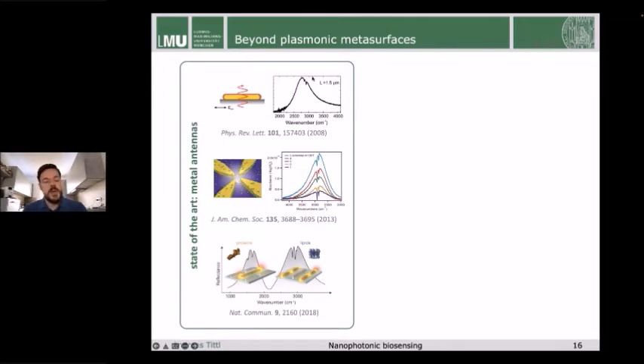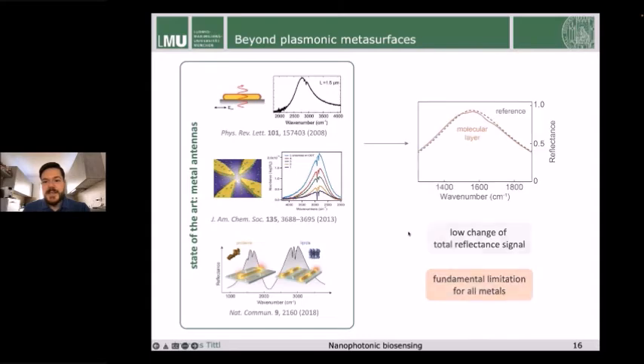And the vibrational bands that we want to detect are actually these very tiny narrow dips here in the line shapes. You can see it in the top, in the middle, and also in the bottom spectra. And this is a fundamental limitation of all metals, that in the infrared they have significant losses. So if you see the resonance here, before and after application of a molecular layer, you see that most of the signal from this antenna system actually remains unchanged. All of the signal remains the same, and we have only a slight modulation here where the vibrational bands occur.